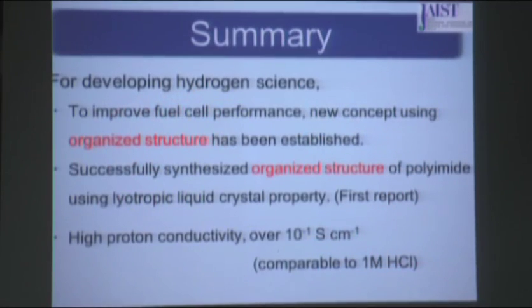So let me summarize. For developing the hydrogen science, the one is to improve the fuel cell performance. New concept using the organized structures has been established. So this is already established. And we successfully synthesized organized structure to polyimide using the lyotropic liquid crystal property. This is the first report on how the proton transport is very high using the organized structures. And this value is very high proton conductivity. This is comparable to the liquid 1 molar hydrogen chloride, very high acidic condition, but that is solid, not liquid.